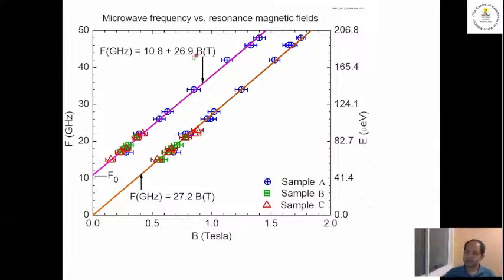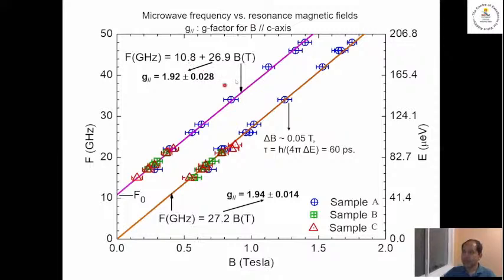We can fit a straight line to both of these, and the slope gives us an indication of the G factor for holes in the system. Turns out if you have a slope of 28 gigahertz per Tesla, that's roughly a G factor of 2. This is 26.9, so it's almost 2. From the slope, we can extract a G factor for holes. We're getting 1.92 and 1.94 for the two curves.